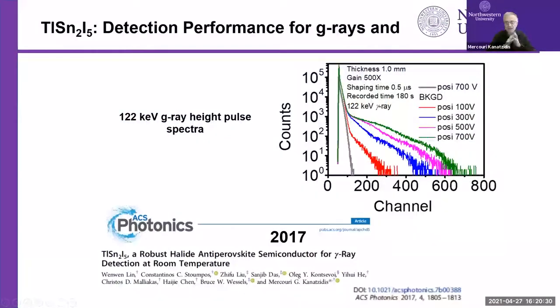We tested this material for gamma rays, and this is what we got. Indeed, it counts gamma rays, and these are the spectra collected as a function of applied voltage across the crystal. That's the good news. The bad news is we cannot resolve the photo peak. We cannot resolve the energy of the gamma rays here using cobalt radiation. So this may be promising with more work that could make it resolve the gamma rays.